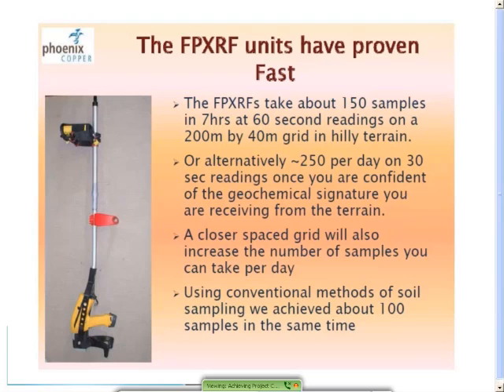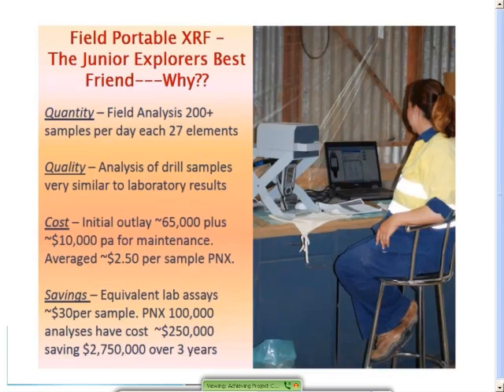Phoenix have the luxury of fine-grained, relatively dry soils and can place the instrument directly on the ground and obtain excellent quality data. We'll show some data that compares results taken in the field with the comparative laboratory data later. Phoenix Copper have found that depending on the sample grid spacing and the topography, hilly or flat terrain, they can take between 150 and 250 XRF readings, which compares with about 100 samples they can collect per day using conventional sample collection for later analysis at a laboratory.